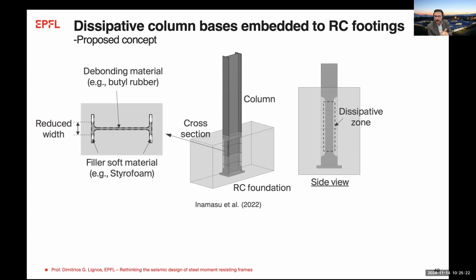Now, with what I'm suggesting, assuming that the residual deformation is not going to be large, there's not going to be demolition. If you have yielding evident in the panel zone, it is a stable energy dissipation mechanism, as we showed. So assuming that your drifts are modest, in one case you would do repairs in the beams because you would have onset of local buckling, etc. In the other case, you would probably have to do nothing because you would have a panel zone that just experienced yielding, and that yielding can carry on until very large drifts without having to do anything.